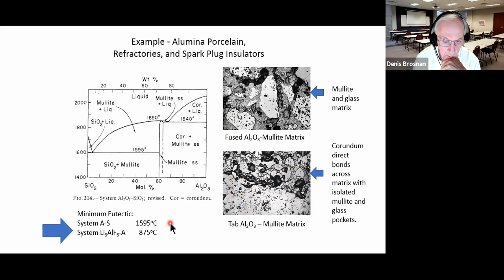to form. The minimum eutectic can be pretty high, about 1600 degrees Celsius. If we use some active fluxes, some lithium aluminum fluoride phases, for example, eutectic can get down to about 875 degrees C or thereabouts. So we can form glass at a little bit lower temperature than the normal, as in porcelains. That again is the advantage of the intensive mixer. We can use a very small amount of a very active flux, and we can disperse it readily throughout this matrix and be successful with what we do.